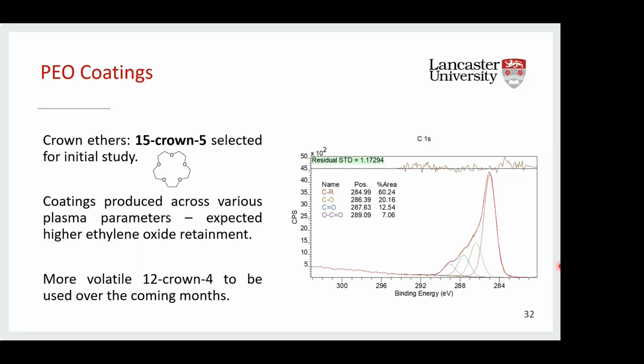Now, despite the smaller 12 crown 4 monomer being used in the research that we've based our experiments on, we decided initially to work with 15 crown 5. This is just because it's much safer to work with and it incorporates more carbon and oxygen, so theoretically you would assume it would make better coatings.